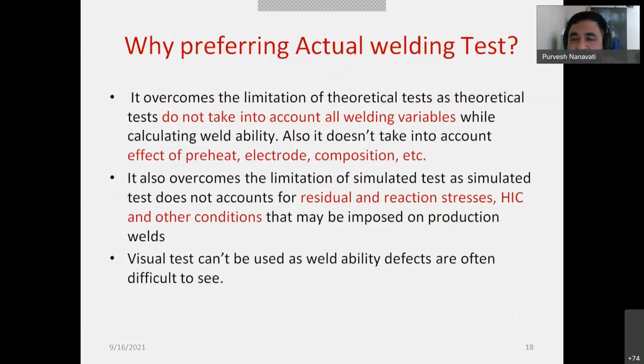Okay. Now moving further. Having discussed this theoretical test, you may now realize that this theoretical test, like what we have gone through, the carbon equivalent and those assessments on the WRC 1992 diagram, will not take into account the welding variables, right? Indirectly, we assume some dilution depending on the heat input. But during the actual welding process, heat input has a tremendous effect, right? So during the actual welding, heat input may be different, right? So these predictive diagrams will not give a clear picture, but they are most of the time used for predicting whether the materials will be weldable or not.